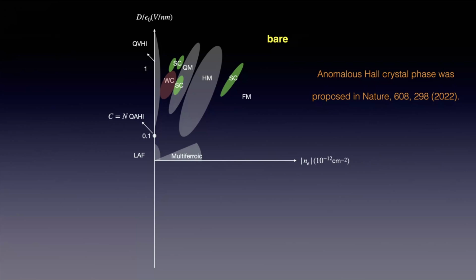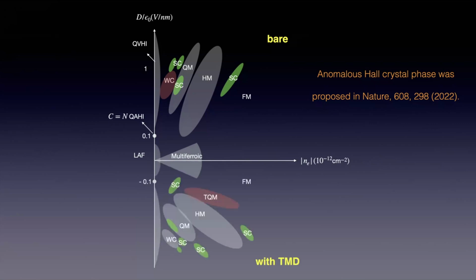Okay, thanks, Allan. And of course, we can also add a TMD to the system, right? So similar physics also occurs when the system has modulated interaction strength and spin-orbit coupling. Okay, so it's pretty similar. As we show in this paper with the MIT group, once you add a TMD, the three-quarter metal phase does appear. So three isospin flavors appear at the Fermi energy. It's also a Stoner magnet.